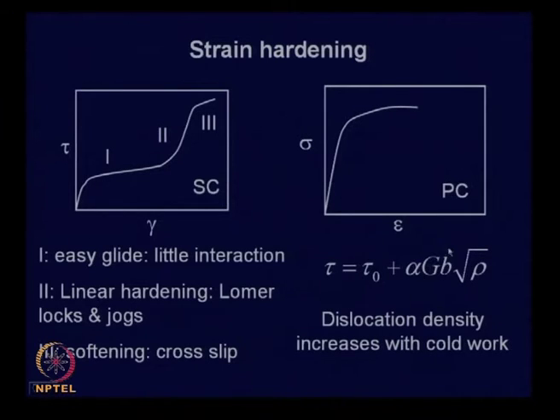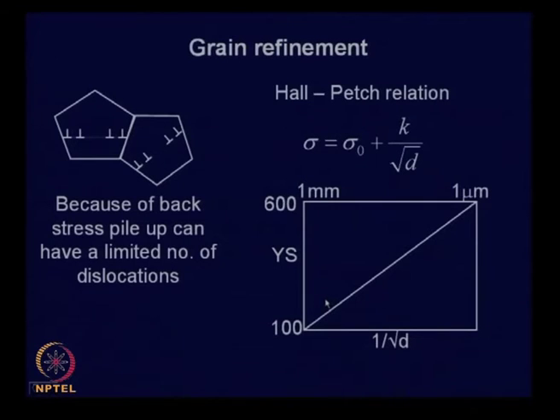Here G is the shear modulus, b is the Burgers vector. So, the main strain hardening mechanism is primarily increase in dislocation density, and the dislocation networks become very fine, dislocation distance becomes smaller, and the strength increases. Another important strengthening mechanism is grain refinement. When a dislocation source acts, let us assume these are the 2 grains. If a dislocation source is operating, it will generate dislocations, and when it moves through the slip plane, it deforms the grain. And in doing so, it can come across a barrier, and